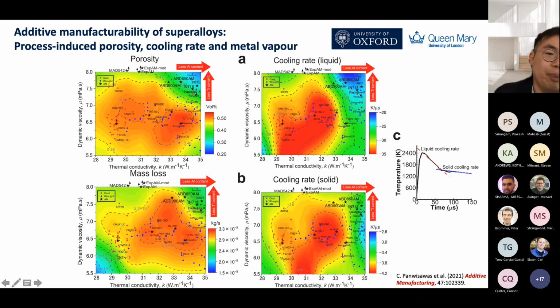as well for superalloy. And then you will see from this, nearly about 35 calculations here mapped in a contour, that the newly developed composition for additive manufacturing actually sits in the good printability region, where you have less porosity, less mass loss, and also the cooling rate is not very extreme compared with some high gamma prime former superalloy.